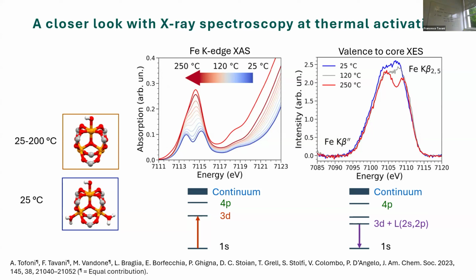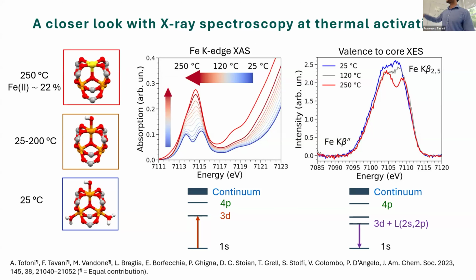So these two transitions are related to octahedral iron, and then the single peak is related to the presence of five coordinate iron. And then once we go up to 250 degrees, we are removing the hydroxyl and reducing the third iron site to iron 2. And this leads to the significant shift of the edge energy towards lower energies. And also the valence-to-core XES, which is basically the iron K beta 2,5, is sensitive to the covalency of the system. It is also sensitive to these structural changes.